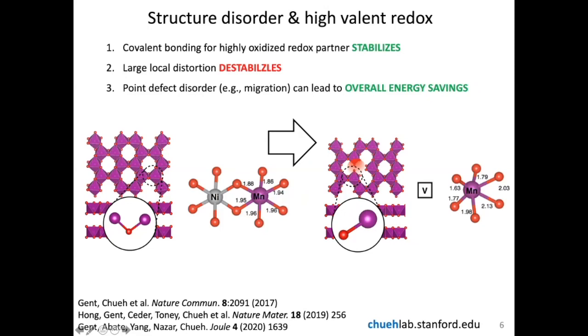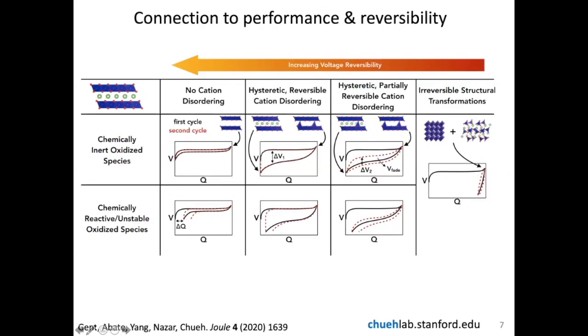So let me come back to my slide on the design rules. This table here shows the various possible modes of voltage degradation and hysteresis when you start increasing the voltage of the materials. On the right, you have very irreversible processes. For example, oxygen leaving from the material, you have completely irreversible transformations, the battery doesn't work. Then you have partially reversible disordering. This is when your metal ions can move back and forth. You get a large hysteresis, and then over time, maybe some of the oxygen is lost from the material,